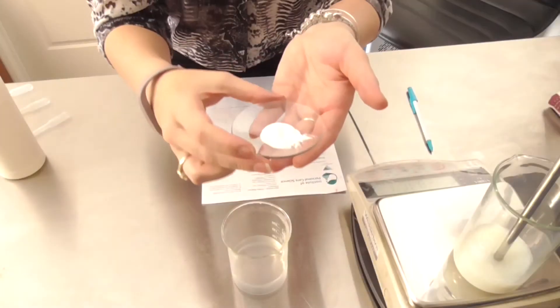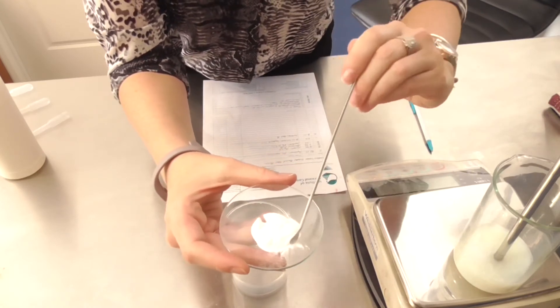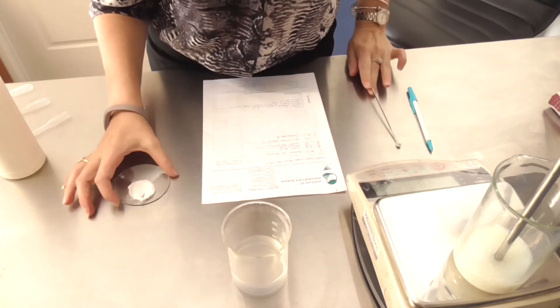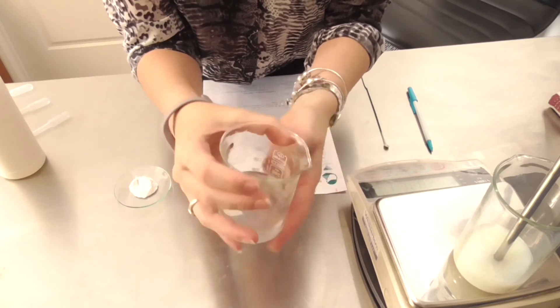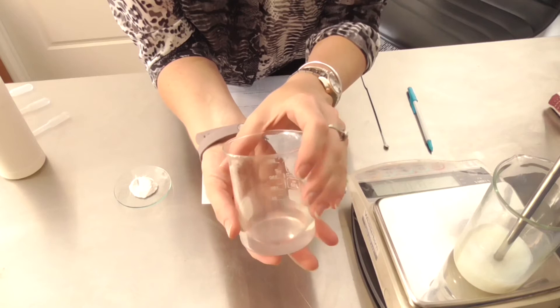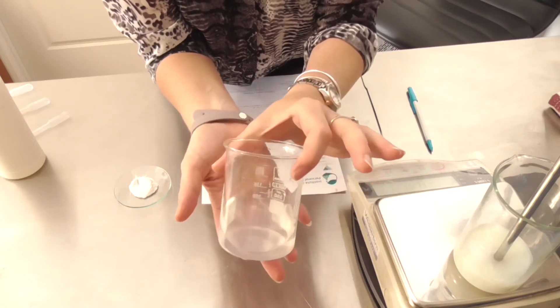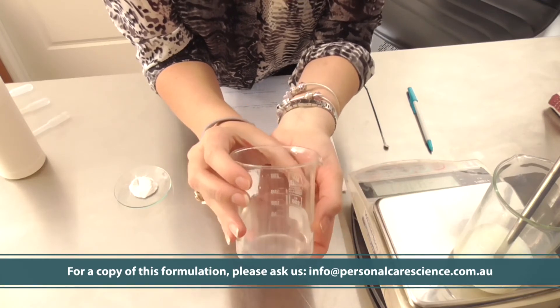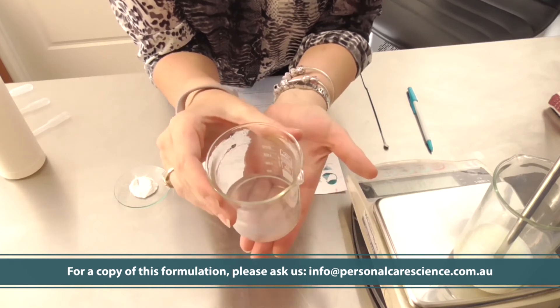So now let's get started. One of the first things you'll need to do is to hydrate the Laponite. It comes as a powder like this, and you need to hydrate this in water first until it is reasonably clear. This is very important — it takes high shear. It will take a good 45 to 60 minutes at high shear. This is a shear-thinning rheology modifier, and it's really important to make sure that we can stabilize the pigment over time.